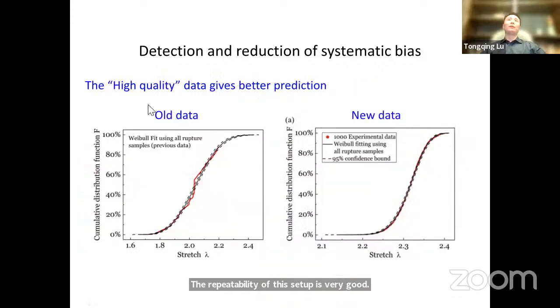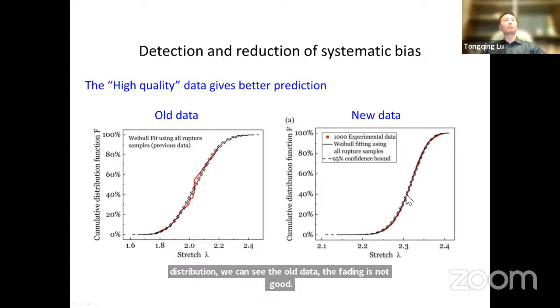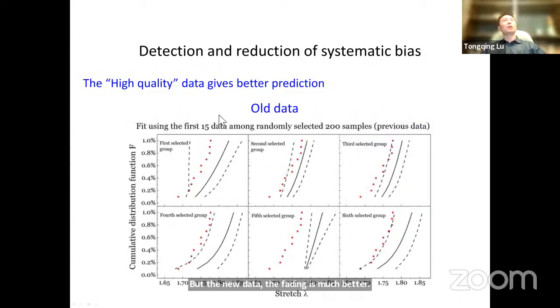Okay, so now we have the new data and the old data. We can easily compare the difference between these two data sets. So first, if we use the data to fit a Weibull distribution, we can see for the old data, the fitting is not good, but for the new data, the fitting is much better. And if we use the data to predict the rare event fatigue.